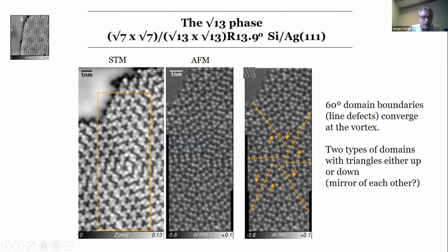Basically, you can see that the structure is formed by different domains. In some domains, we see triangles pointing down. In other domains, we see the triangles pointing up. And there are domain boundaries where you can see lines like that. Here they are signaled. They make about 60 degrees between them, and they all converge in a vortex with this kind of super chiral nature. Okay.